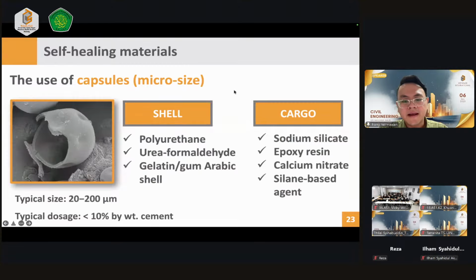Okay, so with the use of microcapsules, it also depends on the type of material that we use for the shell or the cargo. For the capsule shell, we can use either polyurethane, urea formaldehyde, or gelatin or gum arabic shell. With regards to the cargo, we can also use sodium silicate, epoxy resin, calcium nitrate, or silane-based agents. So these types of shells and cargo are the ones that we have used frequently in self-healing applications.